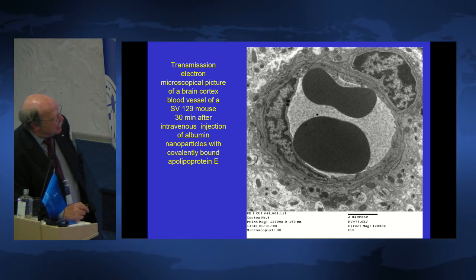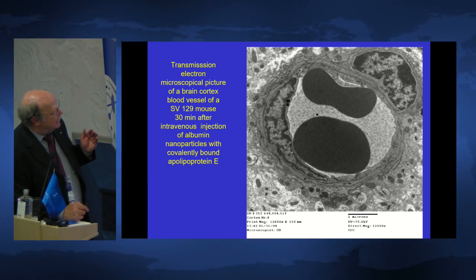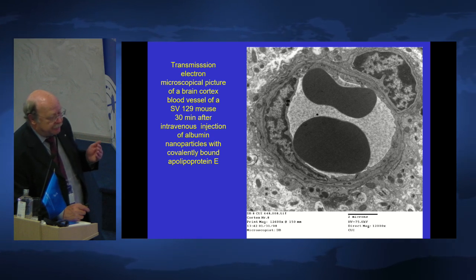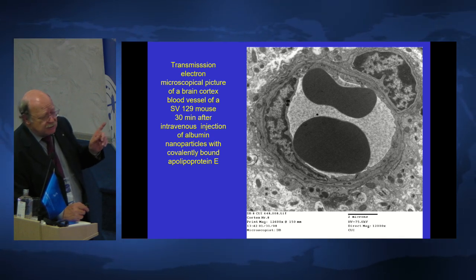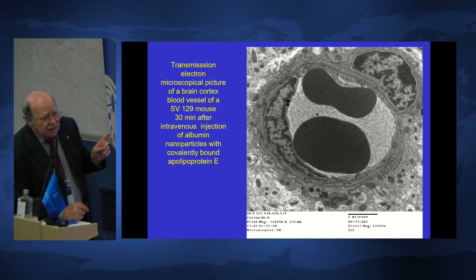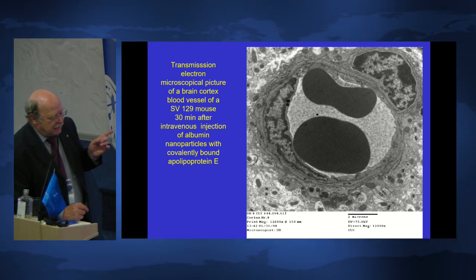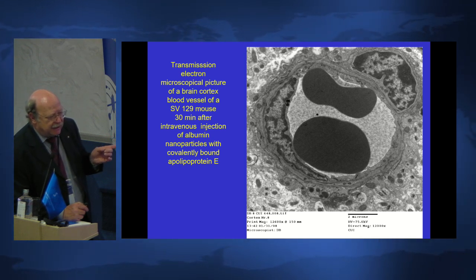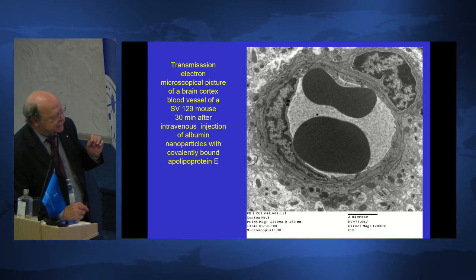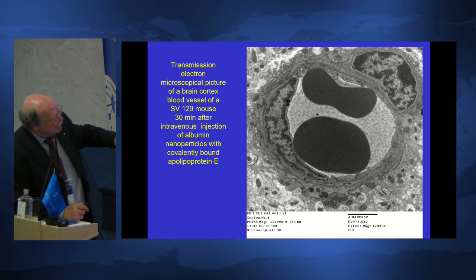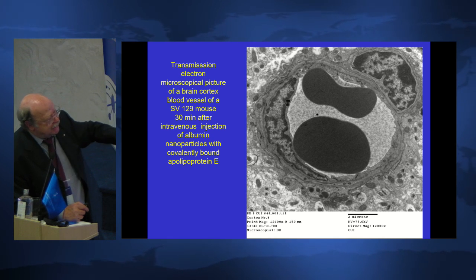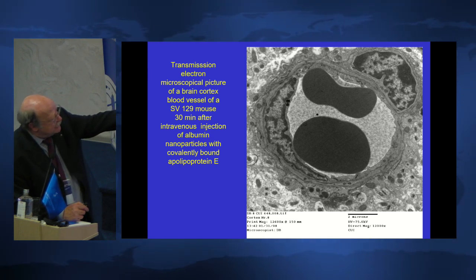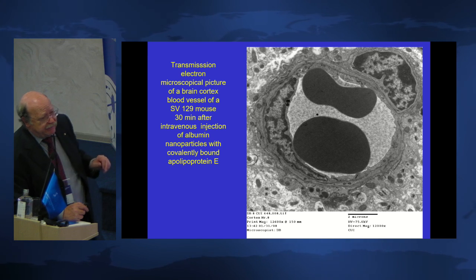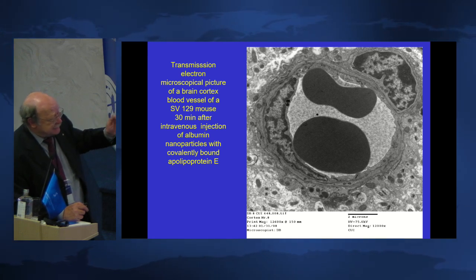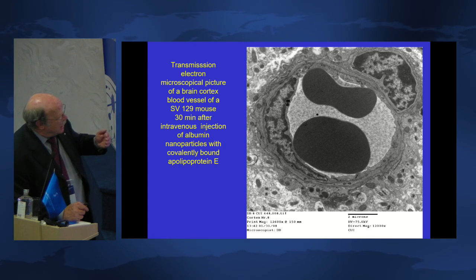At King's College, we were able to do transmission electron microscopical pictures. Here we had to use albumin nanoparticles because the cyanoacrylate nanoparticles and I think also the PLGA nanoparticles are not electron dense enough. This is a transmission electron microscope. This picture is really textbook quality. You see two erythrocytes of these mice, sacrificed after 30 minutes.